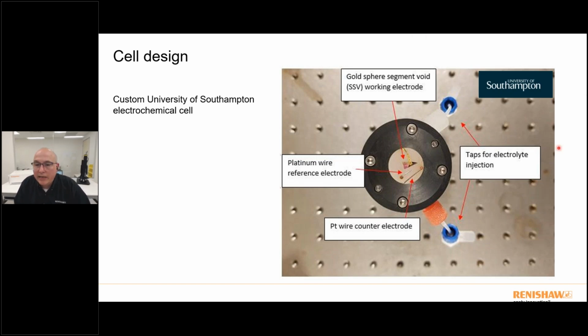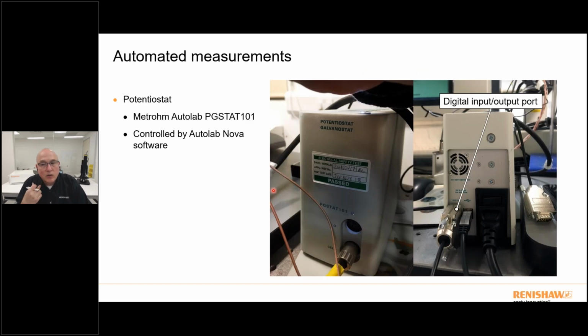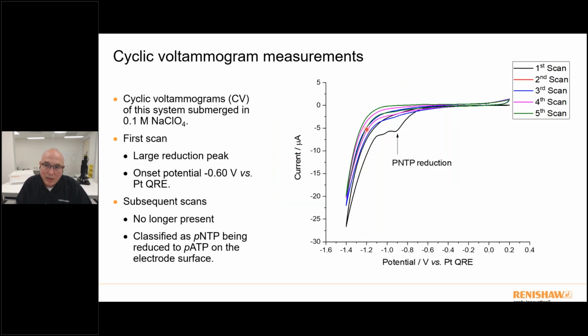So this is a specially designed cell that they have where that SSV substrate was used as the working electrode. And then you have simply taps there. But we're going to look through this window down on that electrode surface and perform these CV experiments. To be able to integrate on the triggering, there was used a Metrohm Autolab with the Autolab Nova software, and that gave us the ability to initiate triggers at different points along a CV gram.